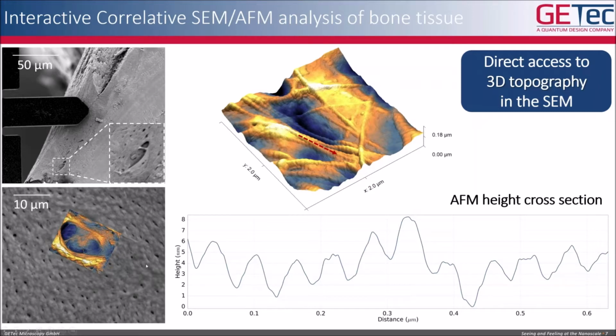If you look now at the scale bar here in Z, which is in nanometers, this also gives you an idea about the noise level that we can achieve with our AFSEM systems. You see that the height change on this collagen fiber surface is around 2 to 3 nanometers.